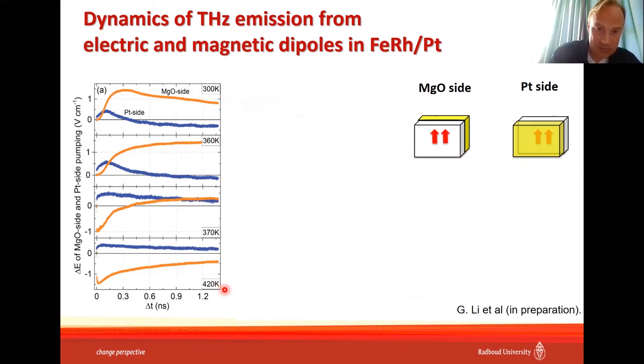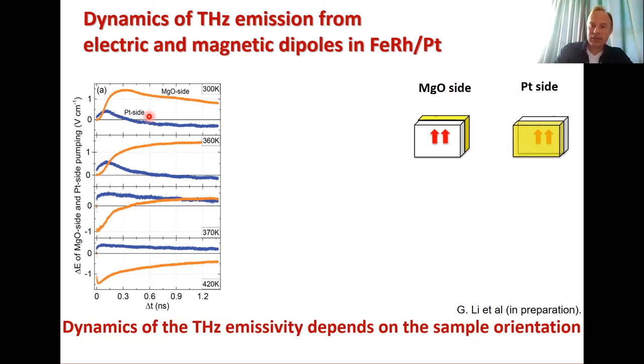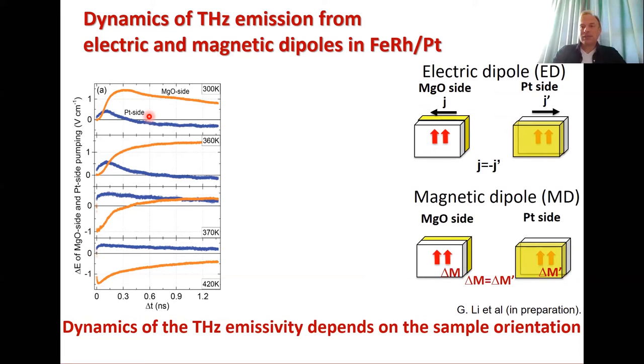360 up to 420. What is confusing in this picture is that if you perform experiments pumping the material from the side of the MgO substrate and from the side of the platinum film, you will see different results. At the end, it is not that surprising because, as I said already, there are two sources of electromagnetic radiation in the medium. There is an electric dipole source and a magnetic dipole source, and these two sources have different symmetry with respect to space inversion. So what you do here, turning the sample, is practically space inversion.